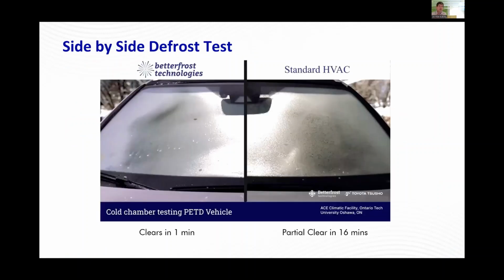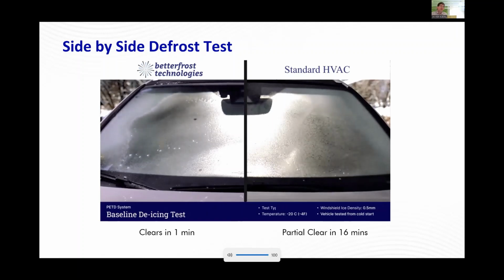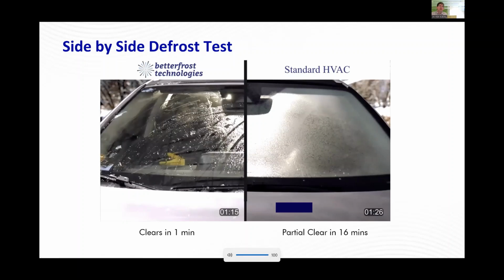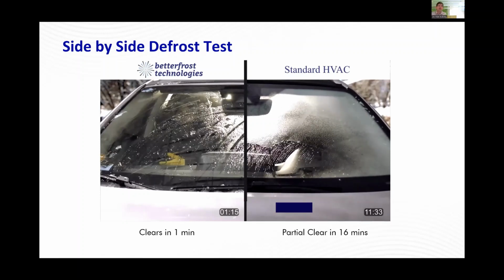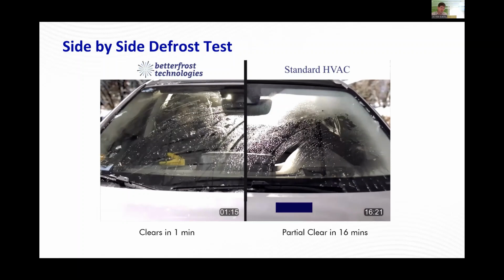We want to show a video of our technology on the left side and a standard HVAC on the right side. And as you look on the left side, you're going to see it go from opaque to transparent very quickly. That's the interfacial layer melting. And with current HVAC systems, what we're seeing is that hot spot in the center, and then it's slowly moving out. This is after 16 minutes, but you have this area where it's completely melted. You have interfacial melting here. That's where you have a thin film of water on it, but where it's opaque, that is still bonded onto the glass. So you can run the wipers all day, but you're never going to remove that until you at least get that interfacial layer melted.